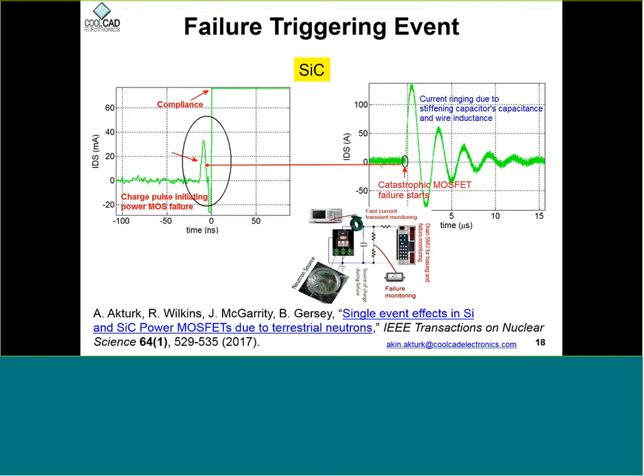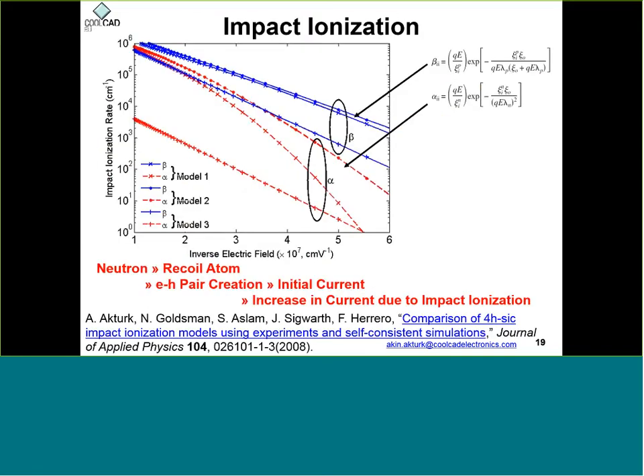Once you see a lot of current flowing through a device, at that point the device has already failed. But if you zoom into the beginning of the failure, you can see there's a small current bump that initiates this catastrophic failure. Using that information, we try to determine what's causing these failures. If we know the root cause, we can design devices that are resilient to this type of radiation.